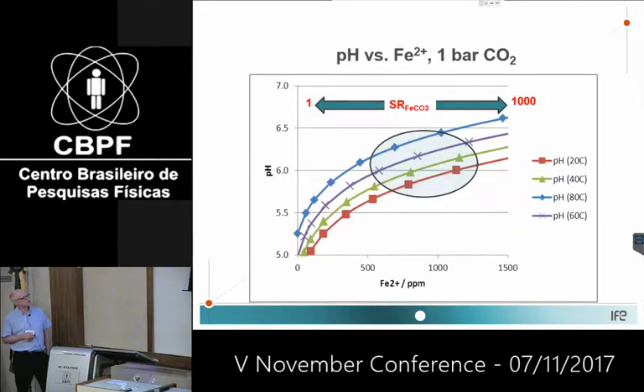So this environment becomes supersaturated in hours, at least days. And this just shows the amount of corrosion product and how the pH increases when you get corrosion products into the system. And it's of course temperature dependent. But usually, at least in lab experiments, we see that we are in this region when it comes to corrosion product for the different temperatures. And that corresponds to a supersaturation of maybe 2, 3, 4, up to 1,000 or 800 times. And when you get this high supersaturation, then you start to precipitate a protective layer.